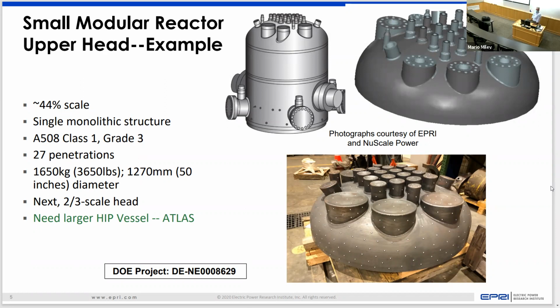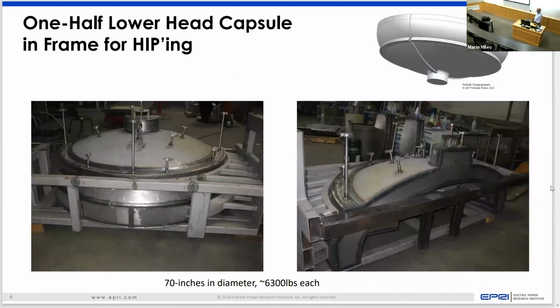This is one single monolithic structure. There are no welds whatsoever. The welds that you see around here are on the can or the capsule that sits on the outside of the powder as it's being consolidated. This thing actually shrinks over time as you put it into the hot isostatic press. It may take you 4 or 5 hours, 6 hours to get to this size. But you can see we can make very complex structures with this technology. So that's why we focused on powder metallurgy and hot isostatic pressing.